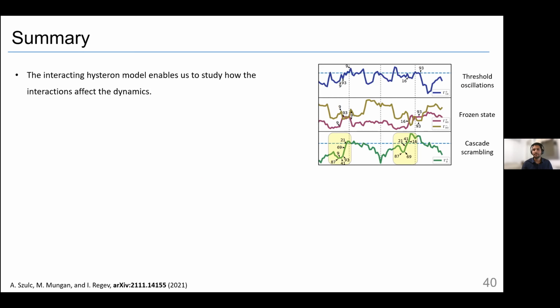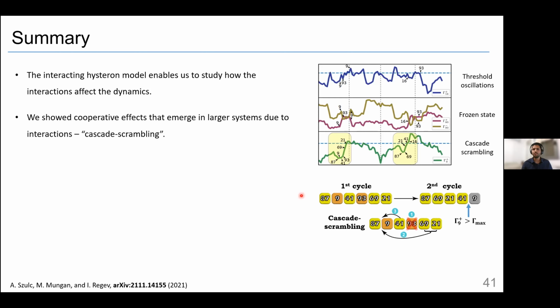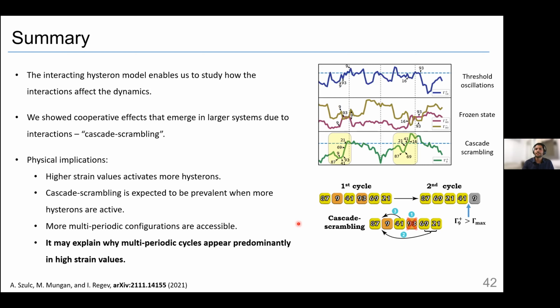And we have many more results in this paper about molecular dynamic simulation that I did not discuss in this presentation. We showed that the increasing number of hysterons is not just a background, but it has an important effect on the dynamics, mainly in the cascade scrambling, as we saw. And the physical implication is that when we have more hysterons, we expect to see more of these cascade scrambling effects, which we believe is the reason why you see multi-periodic cycles more in high strain values than in the lower ones. Because when you have more hysterons, we have more cascade scrambling, you can have more configurations accessible for the system to explore and find, which are multi-periodic.